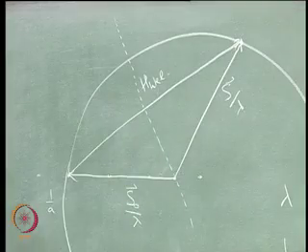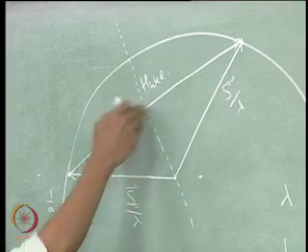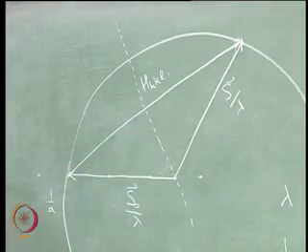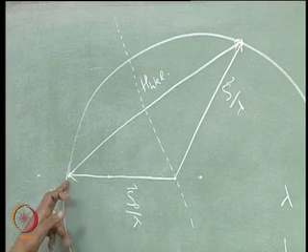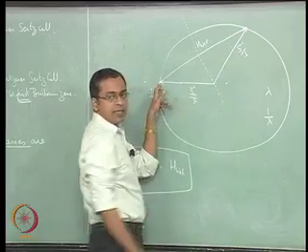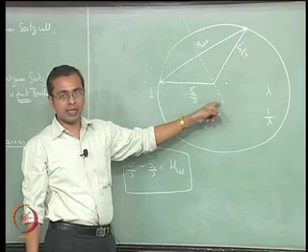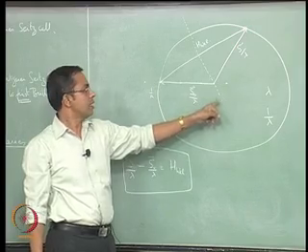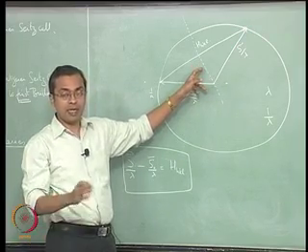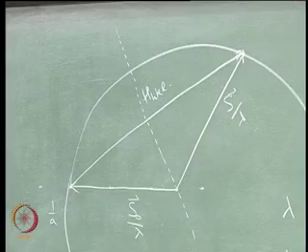So what have we got here? This perpendicular bisector here is actually the perpendicular bisector of a valid reciprocal lattice vector. The origin is this, so the origin is fixed, this is some valid reciprocal lattice vector HKL, I have just drawn the perpendicular bisector to that valid reciprocal lattice vector, and therefore by our definition this perpendicular bisector is a Bragg plane.